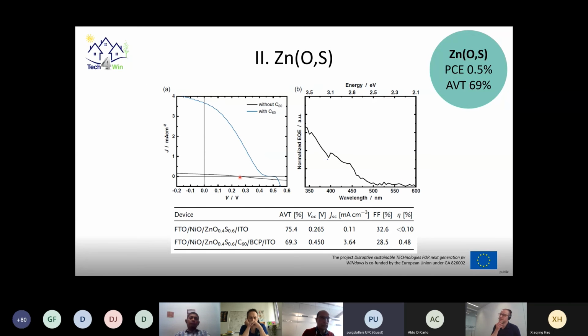If I get now to the cell results, we see here cell results for two different devices, one with the C60 and one without the C60. Without the C60, the result we see is very similar to the zinc sulfide selenide, so a very low photocurrent. Indeed, a photocurrent of 0.11 milliamp per square centimeter. And bringing in this electron transport layer, the C60, is increasing the current and the VOC substantially.